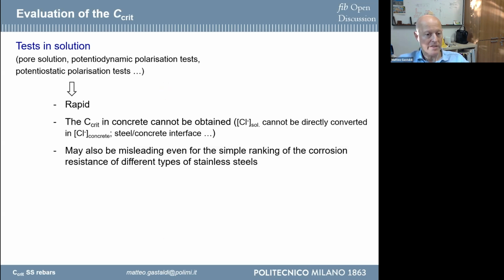This kind of test has the advantage of being a rapid test, and so can give you a result in a few days. The problem is that the chloride threshold that you can find in this condition is not the chloride threshold that you can find in concrete, because, for example, the concentration of chloride that you have in solution cannot be directly converted into the chloride content that you have in concrete. And you also do not have the effect related to the interface between concrete and steel. And so this is very important.